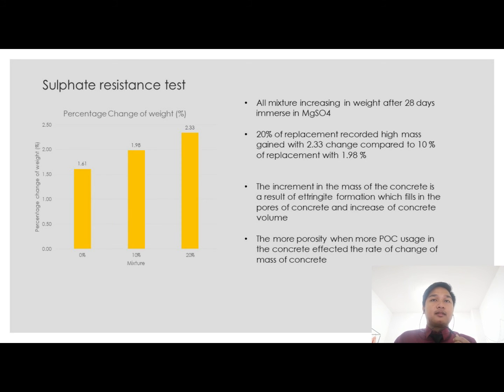Sulfate resistance test. All the mixtures increased in weight after 28 days immersed in magnesium sulfate solution. From the graph we can see all the samples record a change of weight. The change of weight was positive because the concrete has weight gain, compared to the acid resistance test, which has a mass loss.